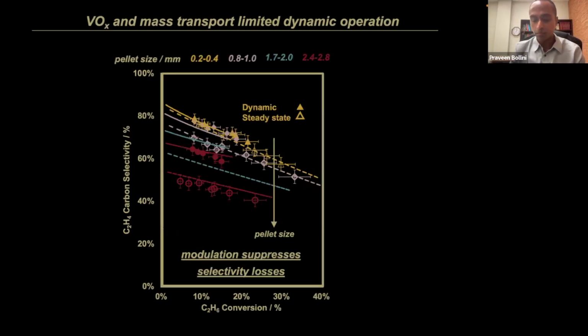So I'll maybe just emphasize a couple of technological or technical achievements here. What I'm showing you here is data on pellets that are larger than what we would typically use in lab scale reactor studies. So we're starting off at about 0.2 to 0.4 millimeter particle sizes, and then extending these to between 2 to 3 millimeters in size, which is approaching pellet sizes that could be used in industry. And what you see clearly is that you have a similar dynamic and steady state selectivity, of course, at the smaller particle sizes, but these selectivities start to separate as you move into larger industrial scale pellet sizes.